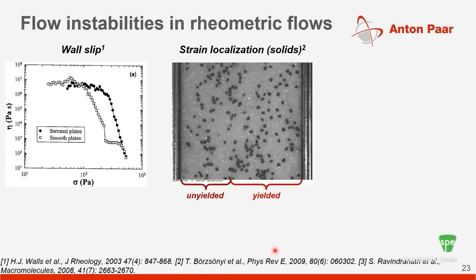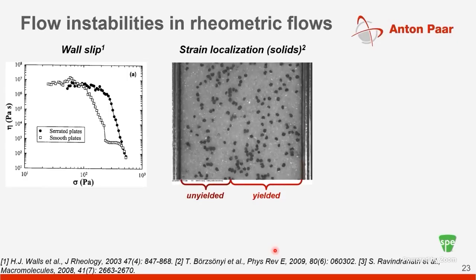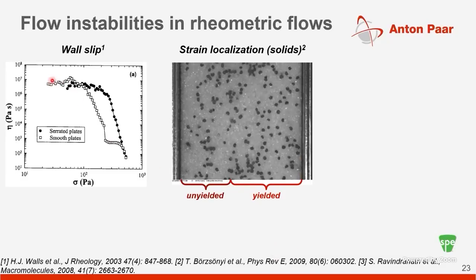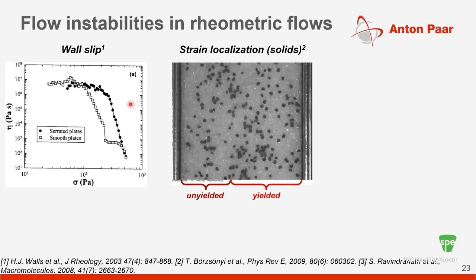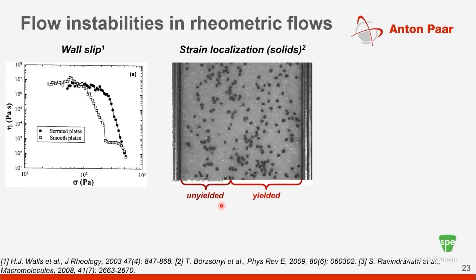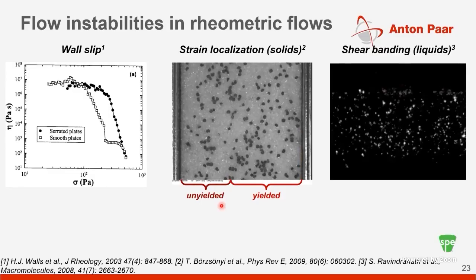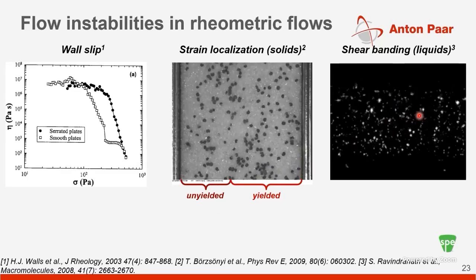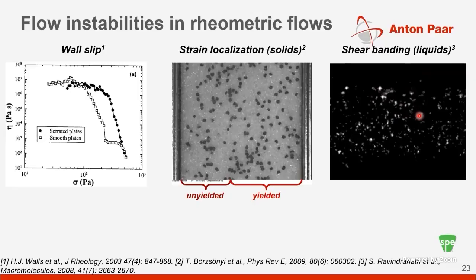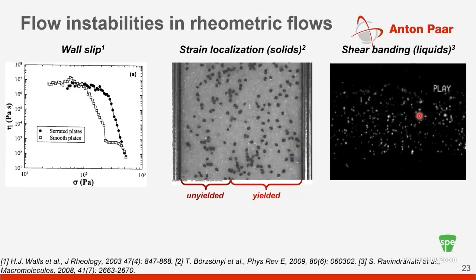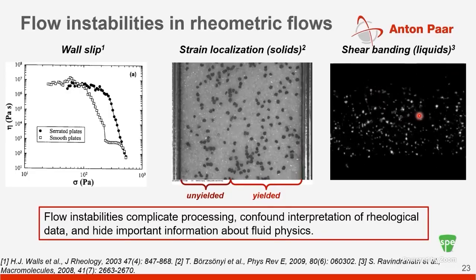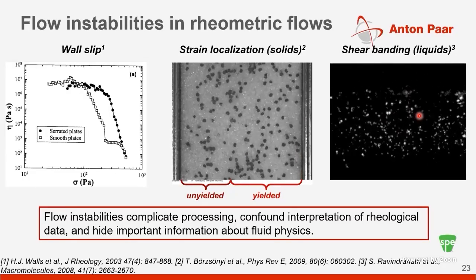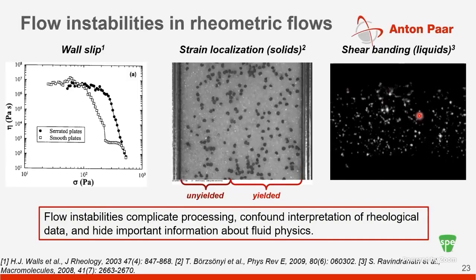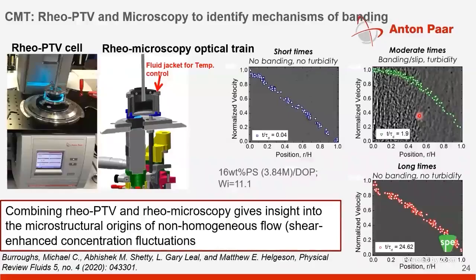We spoke about edge fracture and radial expulsion, but there could be other artifacts in rheology that affect your measurements. For instance, wall slip, which has been studied a lot in literature. There could be strain localization where you have yielded and unyielded regions in your sample, and you could also have shear banding in liquids, which can make interpretation of data very difficult. This complicates processing and interpretation of rheological data, so you need other types of techniques. Rheology by itself doesn't give you the entire picture, so hopefully the next slides will show some other capabilities possible with a multi-drive device.